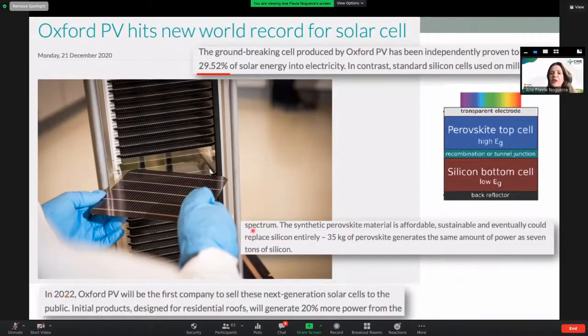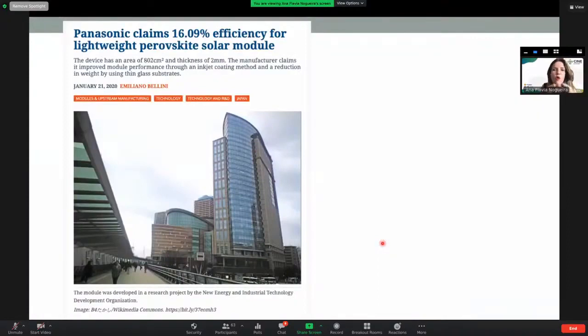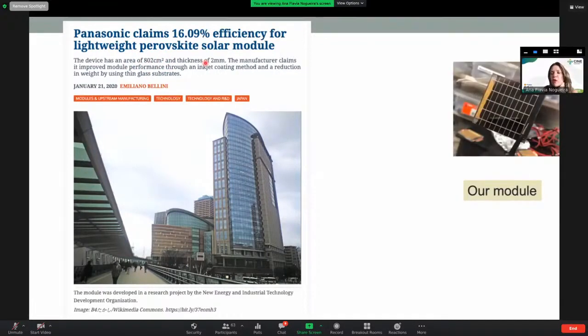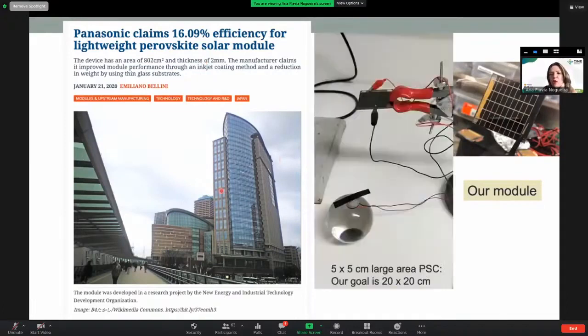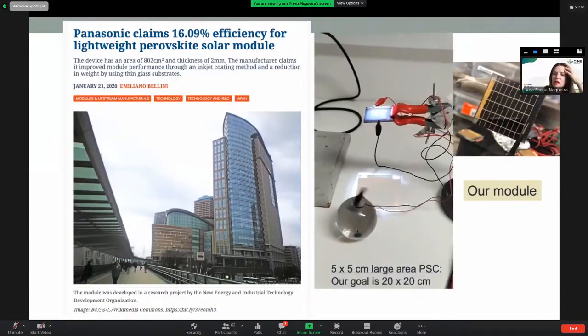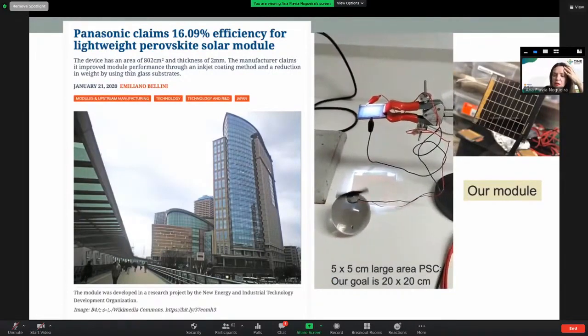Here is just a curiosity about perovskite when you compare it to silicon: 35 kilos of perovskite generates the same amount of power as 7 tons of silicon. But in terms of only the perovskite solar module, the record is 16% in an area of 800 square centimeters, from Panasonic. We're also developing our module in collaboration with Shell in Brazil. You can see here we're expecting to have this module at 20 by 20. This is a demonstration of our module of perovskite solar cells.